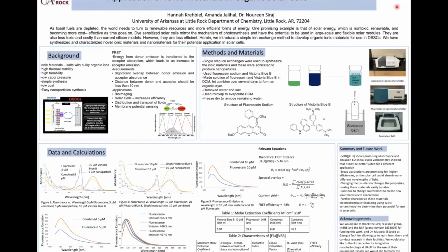We want to generate a dye pair that exhibits FRET, which is Förster resonance energy transfer. It is a non-radiative form of energy transfer, in which energy from the emission of a donor material is transferred to the absorption of an acceptor material, which in turn increases our acceptor's emission. Dye pairs that exhibit FRET have been shown to lead to increased power conversion efficiencies in dye-sensitized solar cells. But in order for FRET to occur, a few requirements have to be met.